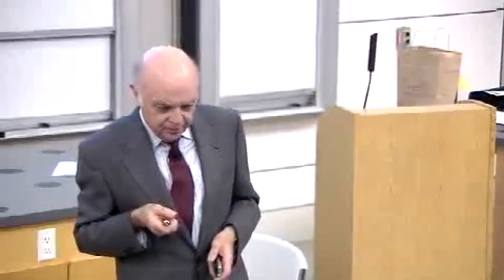The other thing that happens is if you hook up a nanotube and measure voltage and current and let molecules fall on the nanotube, and if you put something on the surface to catch them, you can detect almost single molecules. It's a sensor. It's a nose, and it's actually better than a dog's nose. You can detect almost single atoms. So I can put sensors in this room that would measure how much carbon dioxide is coming from us. I could measure anthrax. I could measure hydrogen. And there are commercial companies that are making these things. So there are practical aspects.